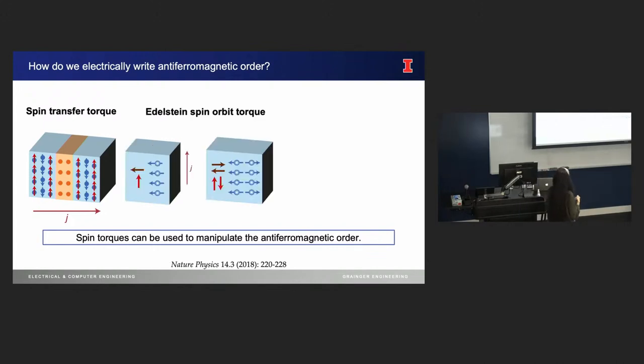The second one is a nice effect. This is a bulk effect. You have this chunk of an antiferromagnet sitting, and you don't need complex multi-layer structures. This effect is called Edelstein spin orbit torque, a complicated name. I can't seem to remember all the torques that are now available in the literature. This one is also called the inverse spin galvanic effect, in case you want to remember that. The idea here is you pass current, and that introduces a non-equilibrium spin polarization, which exchange couples to the magnetization and flips it. This one requires very specific kinds of materials and crystals, ones with broken inversion symmetry. An example in which this has been experimentally demonstrated is Mn2Au.